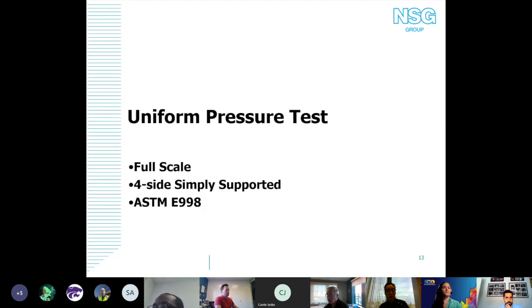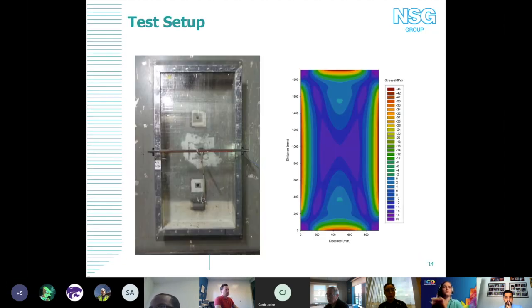Next slide. So now I'm going to move forward to our uniform pressure tests. These are just 4-side simply supported tests. Essentially, we had these large scale tests. We put them in this frame and used a vacuum to create a uniform pressure on the surface of the glass. In this case, we were testing everything with the frit in tension because we knew that was essentially where the issue was. And so, next slide.